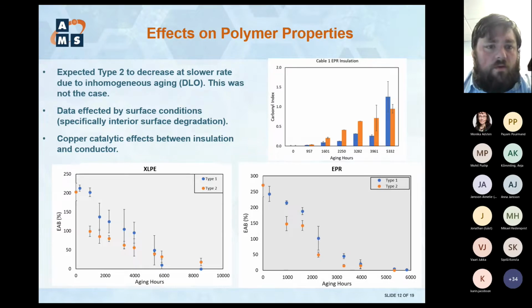So when we did EAB testing, or elongation at break tensile testing, of the type 2 samples, the insulations from whole samples, we initially thought, okay, diffusion limited oxidation effects, that they will age slower, the EAB will decrease slower than the type 1s. But that did not happen. That's not what we observed. We actually observed the orange traces is the decrease we saw in the type 2s, and the blue is the type 1s. We've seen this in XLPE and EPR.